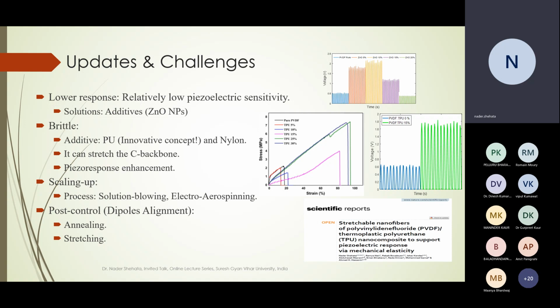However, and this is an innovative concept in the last year, and our group has a good contribution in that, we published recently a paper in Scientific Reports related to it: we can add the polyurethane, for example, up to a certain limit, up to 15%. So we are losing 15% of the initial PVDF, but at the same time, we are increasing the generated voltage. As you can see here from these two graphs, adding TPU, or thermoplastic polyurethane, increases in a very clear way the breaking strain, in some cases exceeding 90%, but it can also increase the generated voltage from the material.